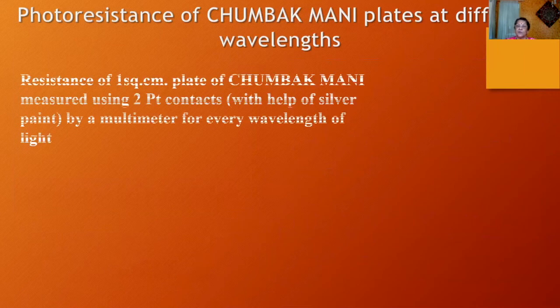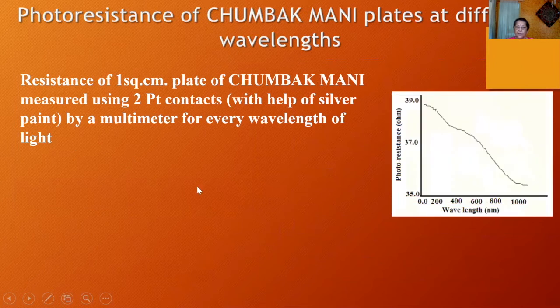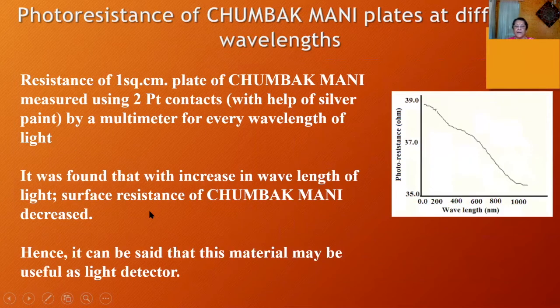Photoresistance, that was an interesting point. So of all the possible analyses that we did, one was the resistance of a 1 square centimeter plate of Chumbak Mani. It was measured using platinum contacts with the help of silver paint by a multimeter. For every wavelength of light we measured, and it was found that with increase in wavelength, there was a decrease in surface resistance of Chumbak Mani, as you can see. So hence it can be said that this material may be useful as a light detector, because it is responding to different wavelengths in a very set pattern.